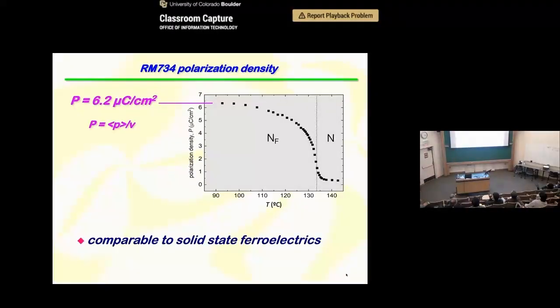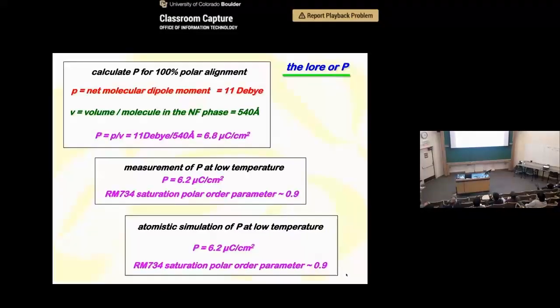Okay, so we measured the ferroelectric polarization. Basically, this is the average contribution to the polarization of an individual molecule divided by its molecular volume in the phase. And so we end up with 6.2 microcoulombs per centimeter squared as a saturation polarization. So we wanted to try to understand this value.